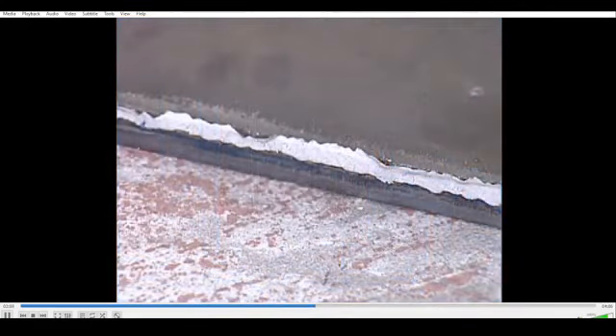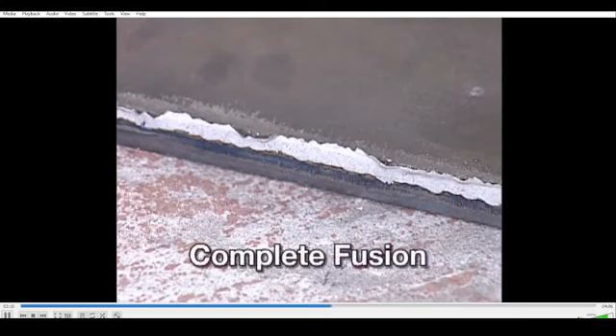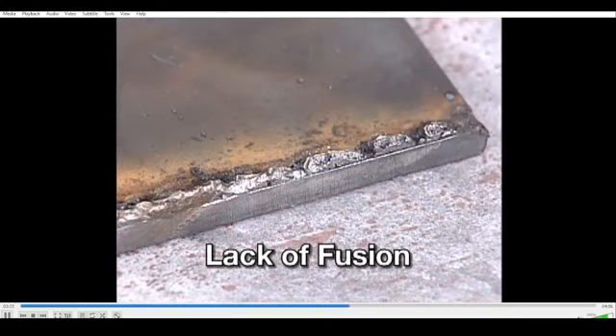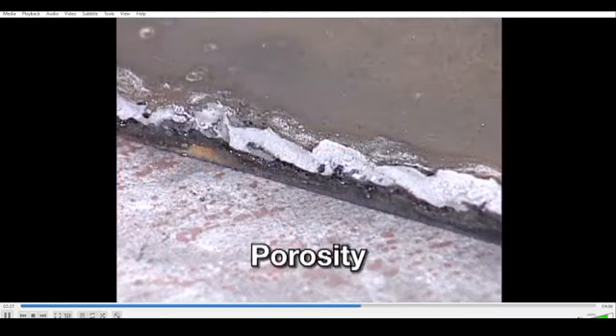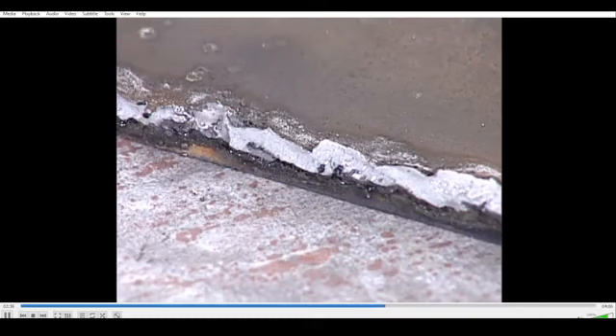The broken surfaces are visually inspected for discontinuities such as cracks, lack of fusion, inclusions, or porosity. Complete fusion to the root of the joint should be evident. Lack of fusion normally appears as unmelted base metal with a clear edge. Porosity appears as round discontinuities on the fractured surface. They may have a silvery color from oxidation. A maximum size or diameter for each pocket, plus a total size are usually stated by the quality specification.